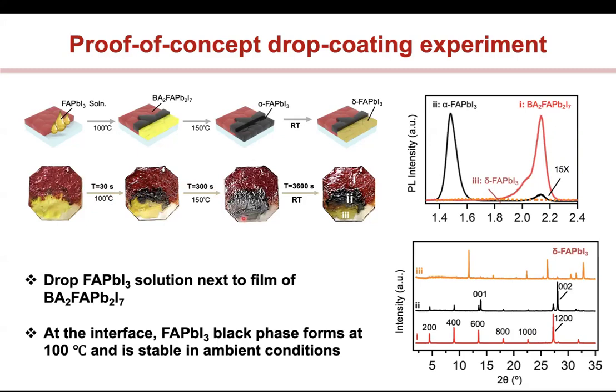But then if I come back to room temperature, if I cool things down, then this part which was not touching your 2D perovskite turns back to yellow, but the middle part always remains black, which is this region 2. And in fact, when you do photoluminescence, you find that this now matches very well with the photoluminescence of your bulk FAPI phase. All right. And so we found a way to stabilize this thing.